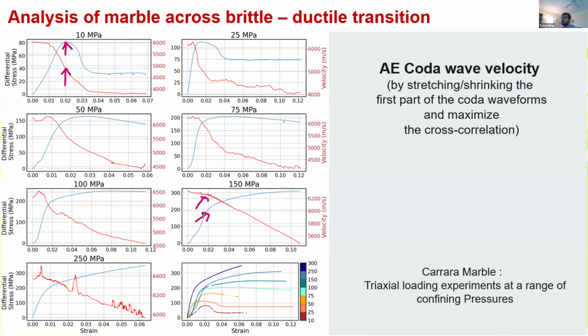So if you look at the 150 MPa one, that's the one on the right, close to the bottom, there's not a characteristic drop like in the brittle case, right? It's more continuous, and it keeps reducing velocity. In the stress-strain curve, the stress keeps building up, right? It's not yielding, it's not dropping, analogous to what it was doing in the brittle case. This 150 is going to be ductile, so it's going to deform very differently.